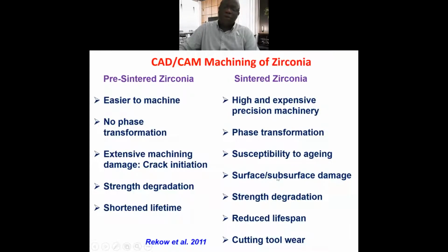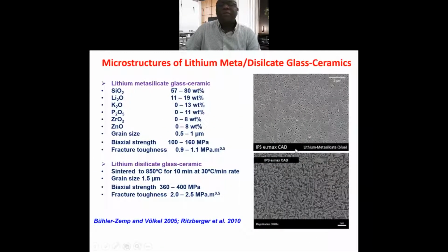This can also lead to surface and subsurface damage, leading to strength degradation and reduced lifespan of the restoration. Cutting tool wear is also common because of the hardness of sintered zirconia. Now, for lithium disilicate, it can also be processed in two structures. One is known as precrystallized lithium disilicate, which is lithium metasilicate, and it comprises silica, lithium, potassium, phosphorus oxide, zirconia, and zinc oxide.